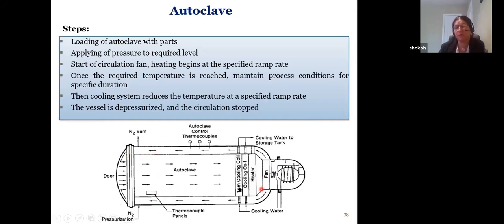This is an autoclave. You load the autoclave with parts, you put them in the middle, and then you apply pressure. In this case, we can use nitrogen. You pressurize to 5 bar or 4 bar. You start the fan for circulation because you want very good circulation at a constant fixed speed. Then you heat up at a specific rate, like 5 degrees C per minute. When you reach the temperature you need, you maintain it for a couple of hours. When the process is done, you ramp down the temperature, you depressurize, and you stop the fan.